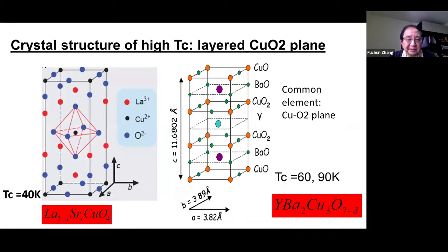Okay. So this is a crystal structure of high Tc. It's a layered copper-O2 plane, and there are many elements. For instance, I consider this, but I want to focus on this copper-O2 plane. And that's the chain in the YBCO. All these high-Tc cuprates have a common element, this copper-O2 plane. And you may ask whether others are relevant. In the very beginning, people made an argument that this copper-O2 plane is most relevant, or that the others are just building blocks to make the system stable.